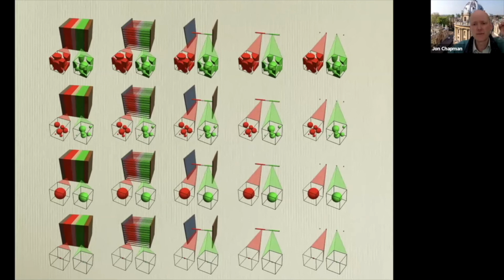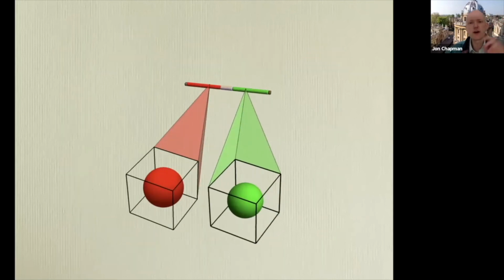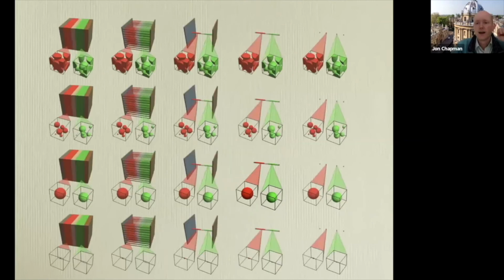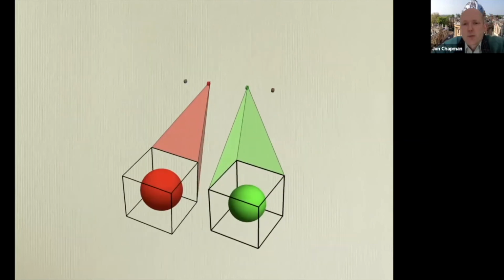Let me pick out one or two models here. So this is where DFN would sit in this. You have a single one-dimensional problem, and at each point in space, you're solving a radial problem for a representative spherical particle. So that's the pseudo 2D DFN model. If I go to the right, then this is where a single particle model fits in.